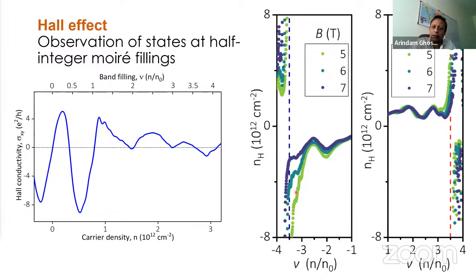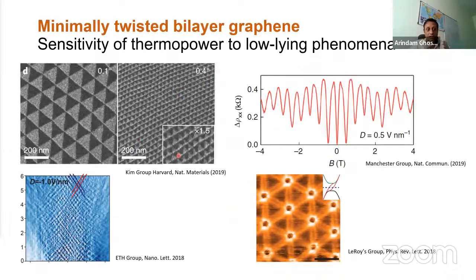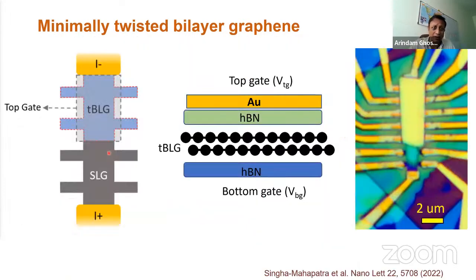I would like to show you there are two aspects. One is this, that if you create a strong spin orbit interaction in this twisted bilayer graphene, you get a new hierarchy of states at 3.5 and plus minus 3.5, which are not understood, where those states are coming from. In addition to that, there are new topological phenomena coming up where you can create minimally twisted bilayer graphene and create topological channels in graphene through reconstruction of the lattice structure. And that leads to these beautiful one-dimensional channels, and because they are a network, it gives a nice Aharonov-Bohm effect that we have been looking at.